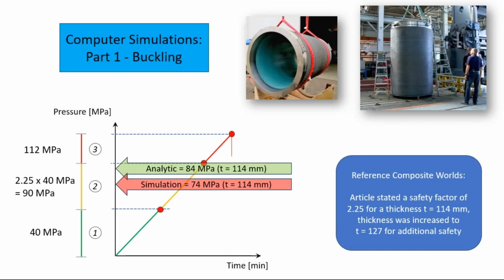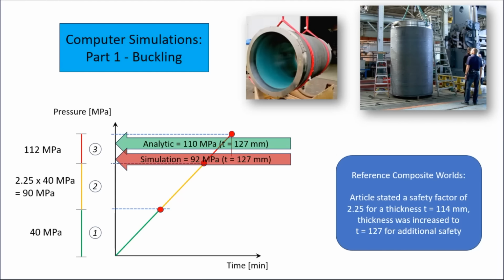If we have 90 megapascals for a thickness of 114 millimeters, the maximum pressure in the safety region would be 112 megapascals for a thickness of 127 millimeters. Instead of 90 megapascals, our simulation shows 74 megapascals, and even if we increase the thickness to 127 millimeters, we barely get about 90 MPa as a design load.